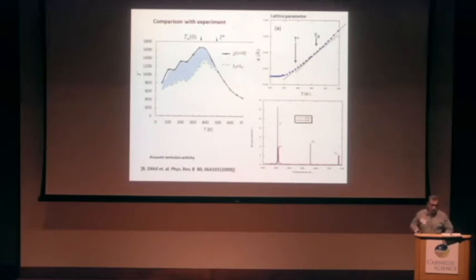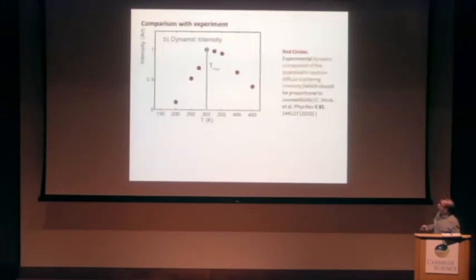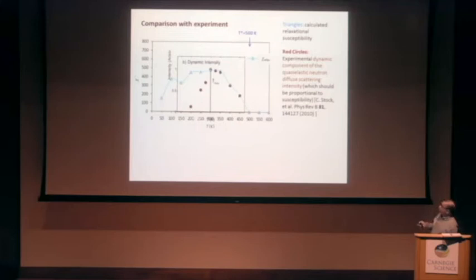But I need to say that this T-star temperature, according to different experiments, is found at slightly different temperatures, and we try to show that there are two T-star temperatures according to our simulations. They are different, and this is another comparison with experiment. This is the dynamic component of quasi-elastic diffuse scattering, and if we fit our relaxational contribution, we see that the shape is very similar. The dashed line is the calculations, and